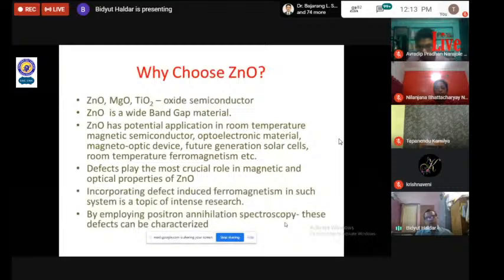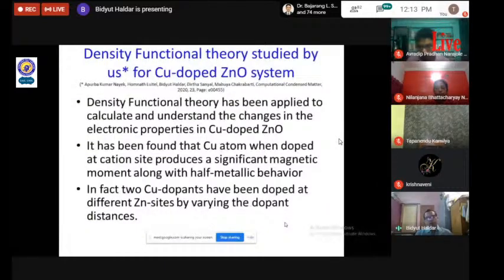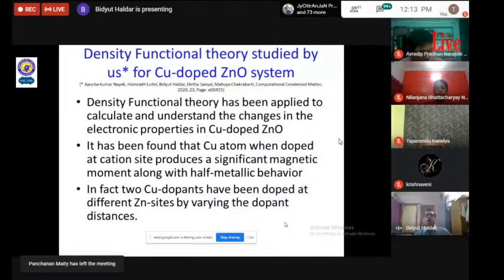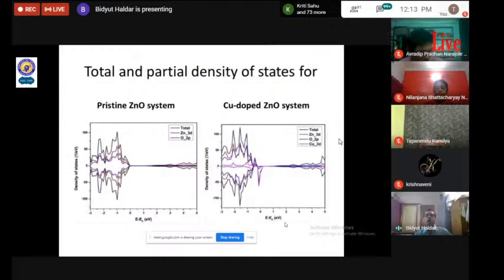In our earlier paper in computational condensed matter, we have done some density functional theory studies on copper doped zinc oxide system in order to understand the changes in the electronic properties. It has been found that copper atoms, when doped at cation sites, produce a significant magnetic moment. Two copper dopants have been doped at different zinc sites by varying the dopant distance. This is all done using density functional theory.